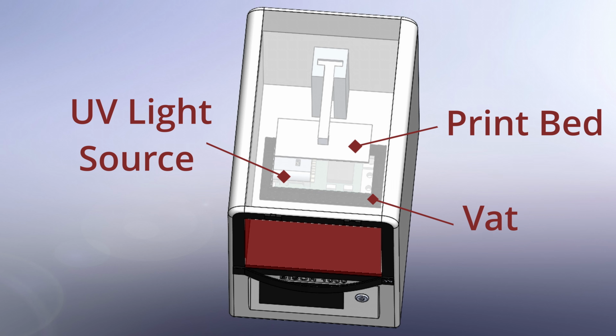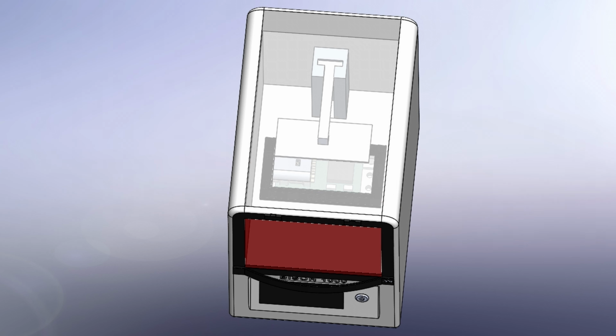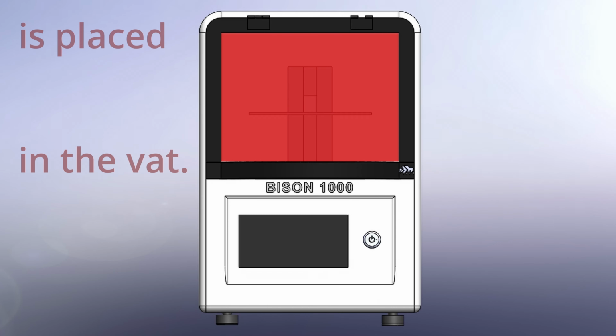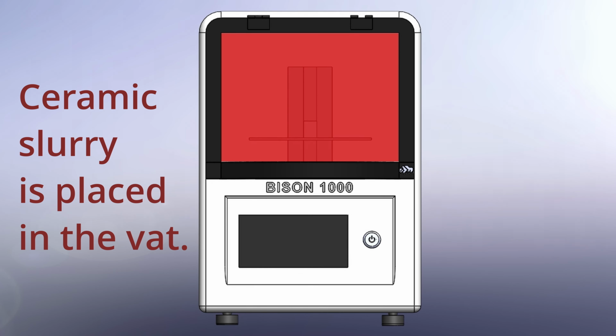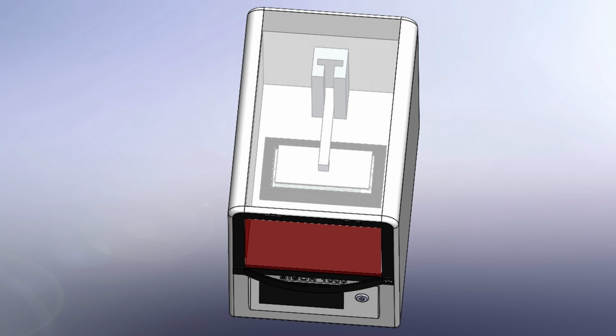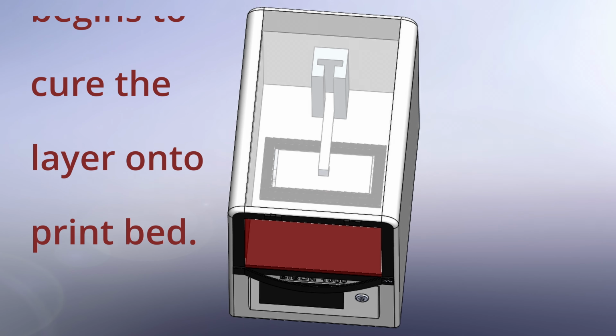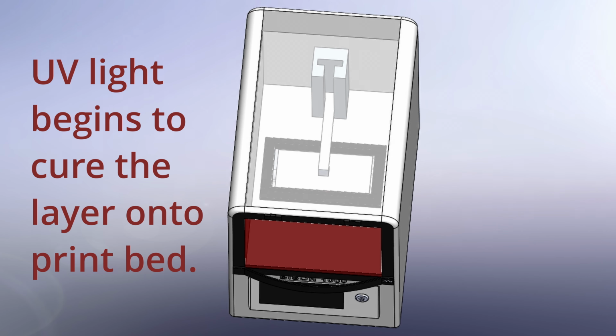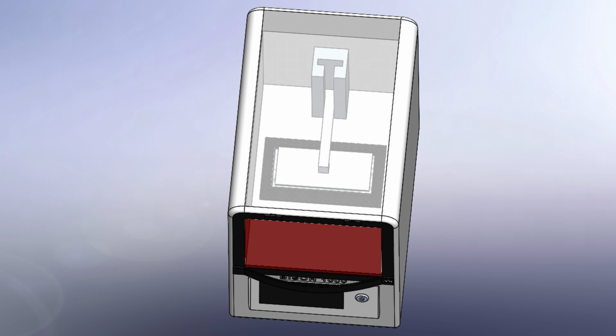The way it works is a viscous slurry is poured into a vat. Then a UV light source cures the photocurable ceramic loaded slurry onto a print bed. The photoinitiators convert the light energy from the UV light source to chemical energy. The photoinitiators cause a chain reaction that causes the monomers and oligomers to cross-link.